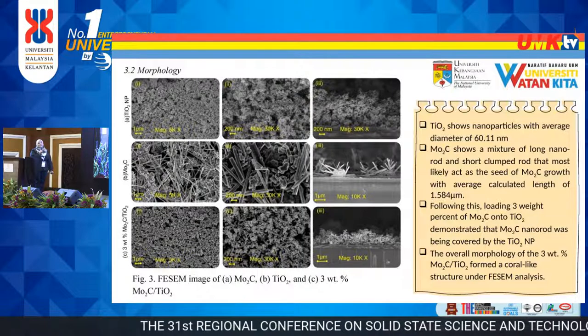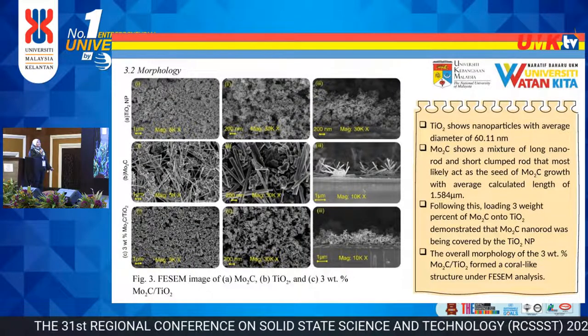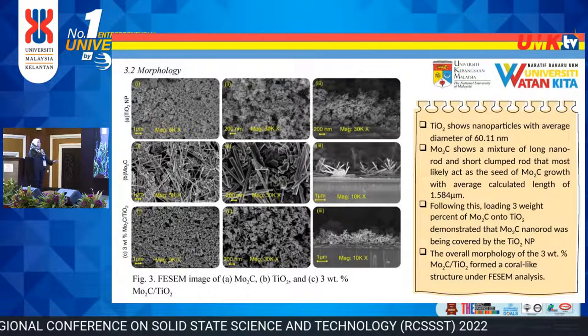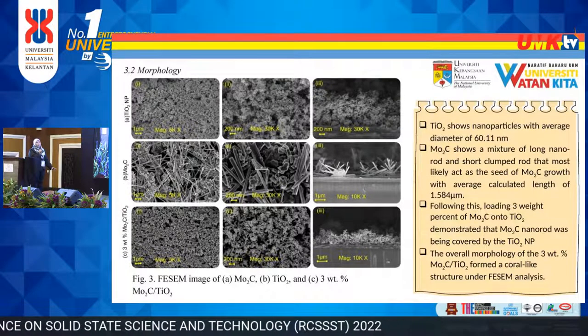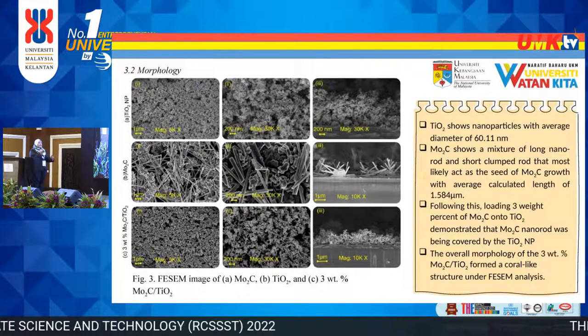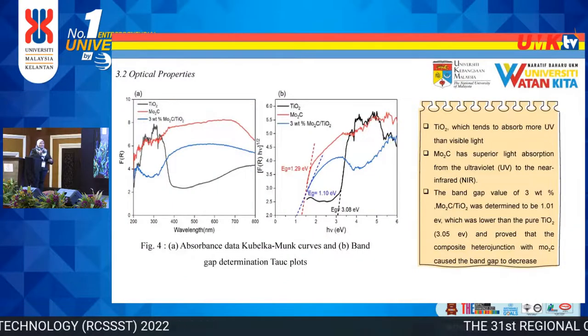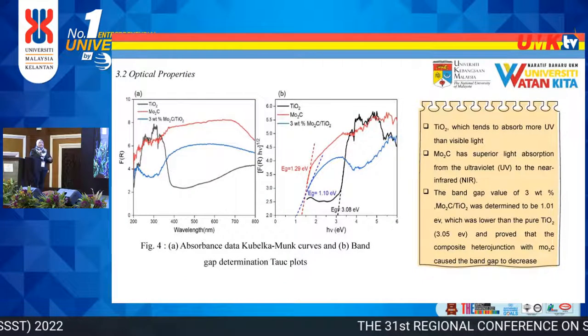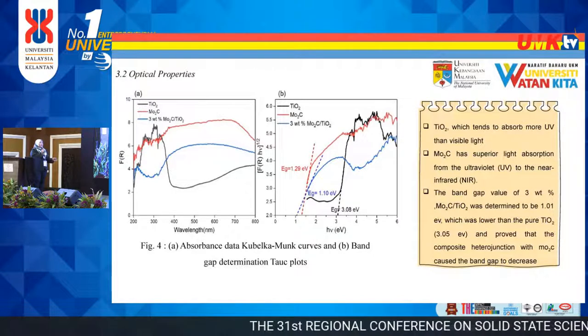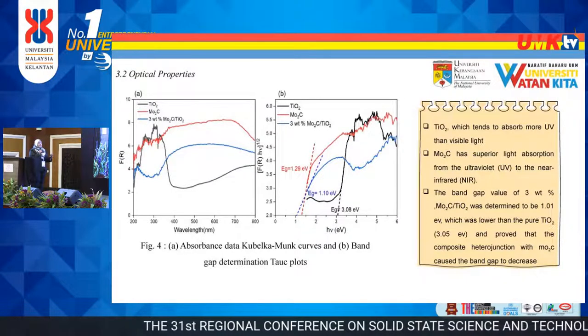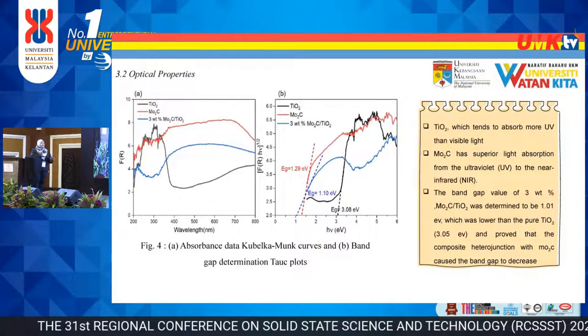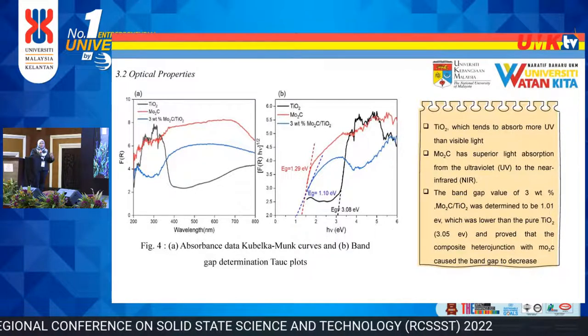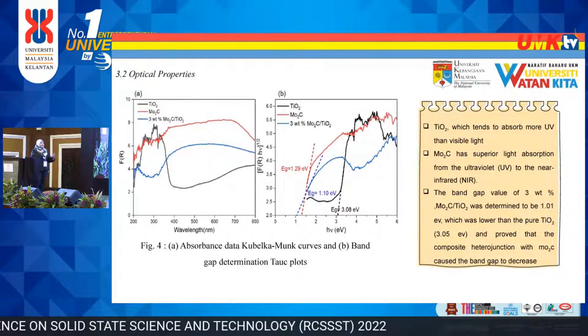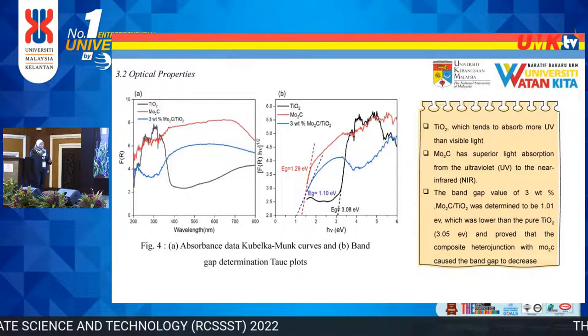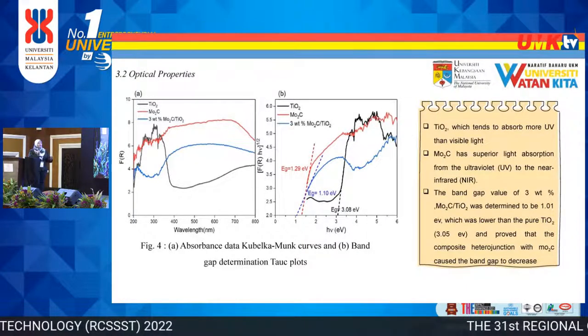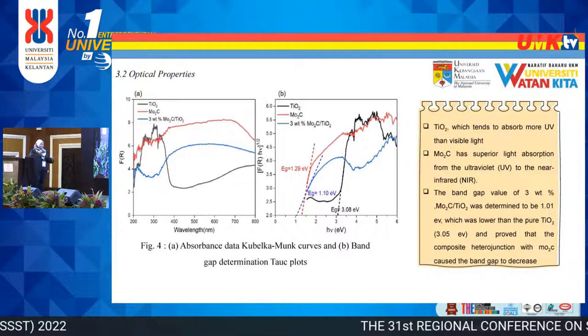Cool. So next, I measured the optical properties of the sample. From figure 4A, TiO2 tends to absorb more UV light than visible. However, molybdenum carbide has superior light absorption from the UV light to near IR. So the band gap value of 3 weight% molybdenum carbide onto TiO2 was determined to be 1.1 electron volt, which is lower than the pure TiO2, and proves that the composite heterojunction with molybdenum carbide caused the band gap to decrease.